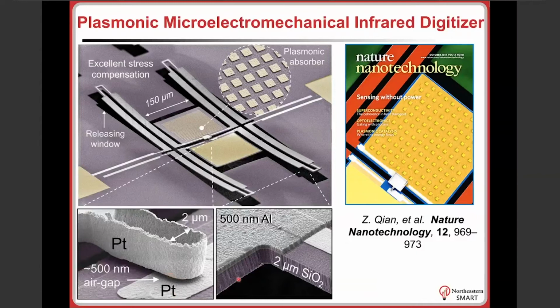Also, I want to point out here the bimaterial structure that I described before. It's about 2 micron of silicon oxide, and on top of that, there is 500 nanometer of aluminum. Those are the 2 materials with 2 different thermal coefficients of expansion that create the bending upon exposure to a temperature variation. And the last thing I want to point out is the plasmonic head that carries the contact tip. You can see that we have this very nice plasmonic structure. These are metal patches, with dimensions in the order of a micron or so. But I want to point out that we really put some effort in achieving smooth edges for these structures in order to get very sharp absorption peaks.